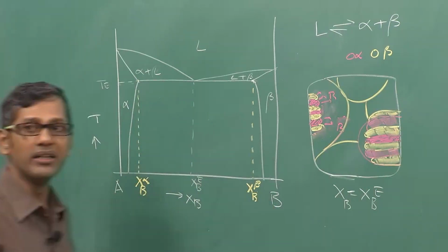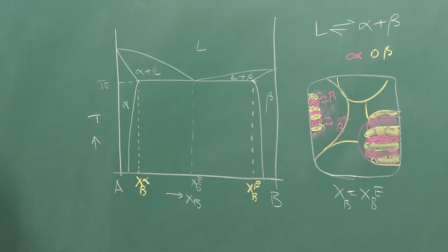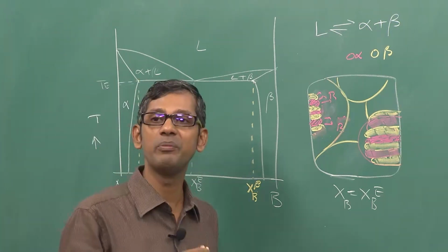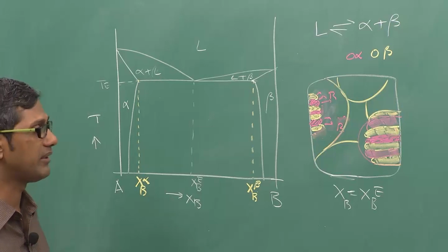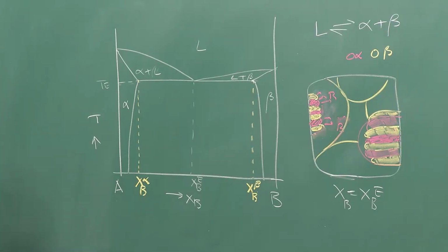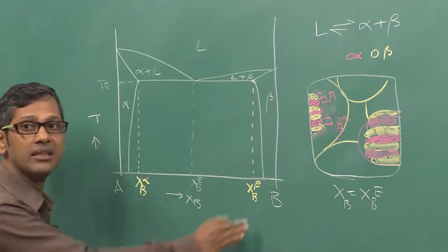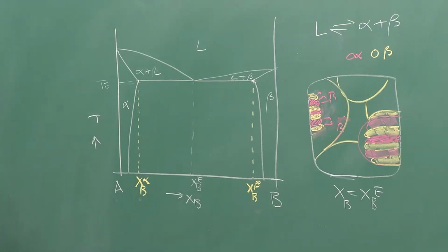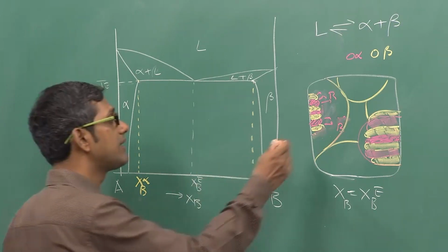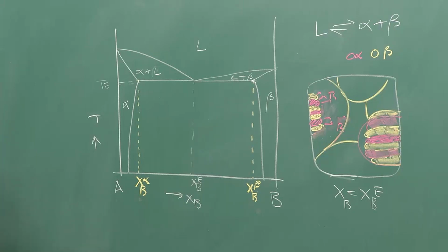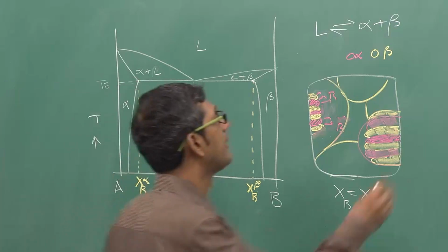Now, the things will be a little bit different when you go from lamellar to rod or even nodular or acicular eutectic, but the mechanism will remain the same. The mechanism is not going to vary, because in all these eutectic phase diagrams one phase will be rich in A, the other phase will be rich in B. So, it does not matter whether you are forming a morphology like lamellar or rod, the rejection of the solute in the liquid and the side regions will be very important. The important lesson which you observe here as compared to a dendrite.